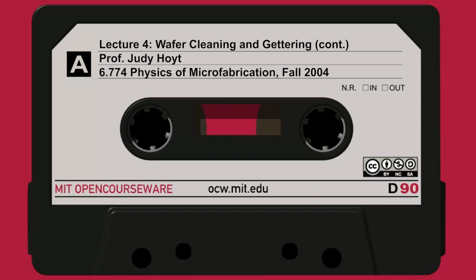And in fact, on slide 26, this is just to remind you of the relative magnitude of the gold diffusion. Look at the gold interstitial diffusivity up here compared to the diffusion of silicon self interstitials. If you have an element like titanium, which diffuses slower than silicon interstitials, it's going to have a more classical type of profile, as shown here on the lower right, for its diffusion profile of titanium out diffusing or diffusing to the back of the wafer.